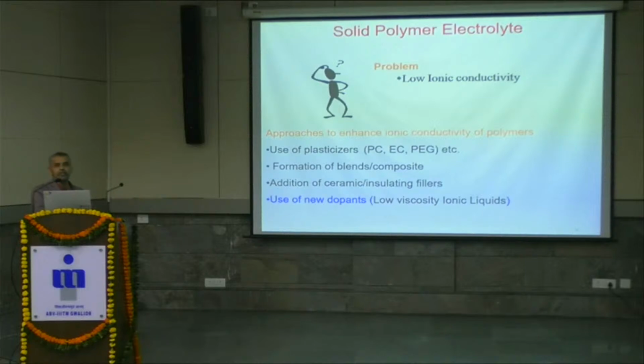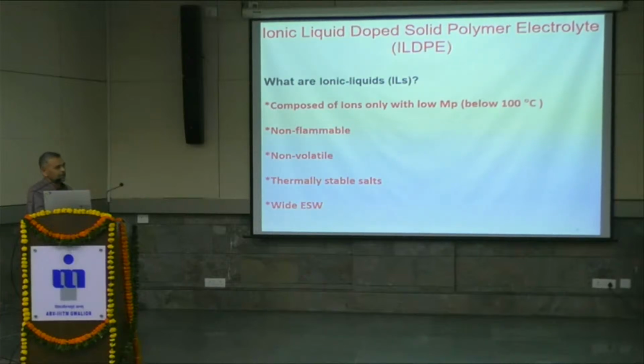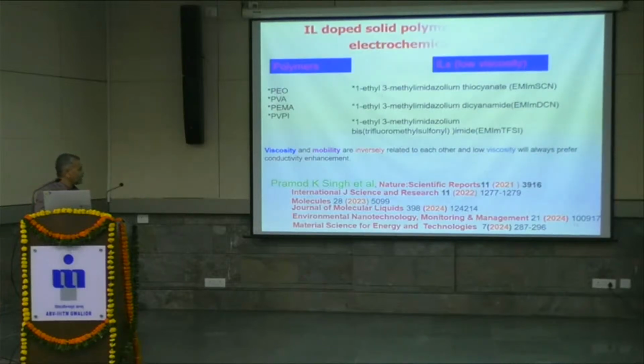Ionic liquid is a very good plasticizer along with being an ionic source. So I purchased many ionic liquids and dope them, directly or with salt, into this polymer electrolyte. And what I found is that the main barrier, the low ionic conductivity, gets removed. So we got a very good conductivity. I am giving you only one example because I have published several papers in recent years, so anybody can go through these papers.